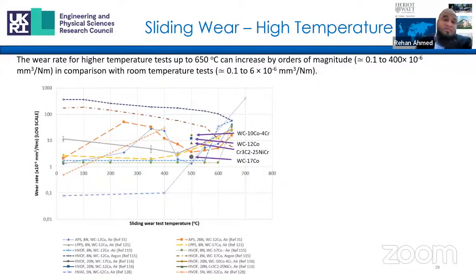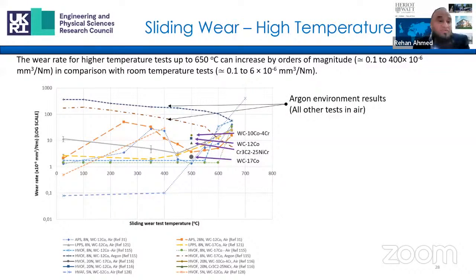At higher temperatures, the story is completely different because at higher temperatures, the wear rate of tungsten carbide cobalt accelerates exponentially. And this is shown on the log scale because we couldn't fit the whole thing in one go. And two factors play an important role as the temperature increases from room temperature to about 650 degrees Celsius. The first factor is the temperature-dependent changes in the mechanical properties of the coatings. As the temperature increases, the elastic modulus and hardness decreases, whereas the fracture toughness is expected to increase. However, due to the microstructural phase changes leading to eta phases at higher temperatures, the toughness also decreases.